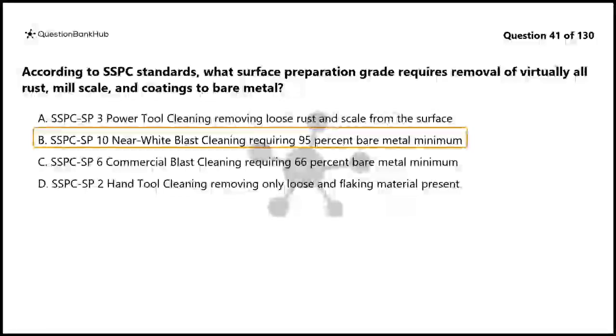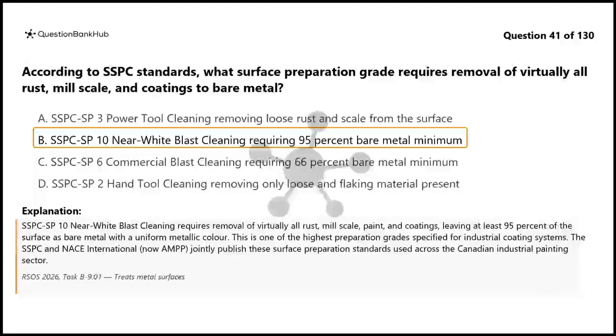The correct answer is B. SSPC-SP10 near white blast cleaning requires removal of virtually all rust, mill scale, paint, and coatings, leaving at least 95% of the surface as bare metal with a uniform metallic color. This is one of the highest preparation grades specified for industrial coating systems. The SSPC and NACE International, now AMPP, jointly publish these surface preparation standards used across the Canadian industrial painting sector.